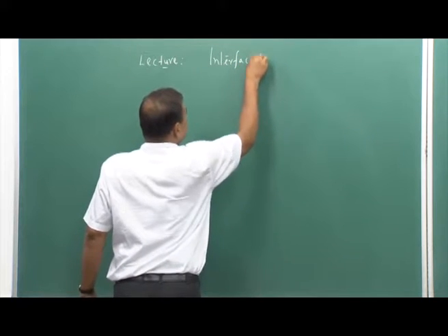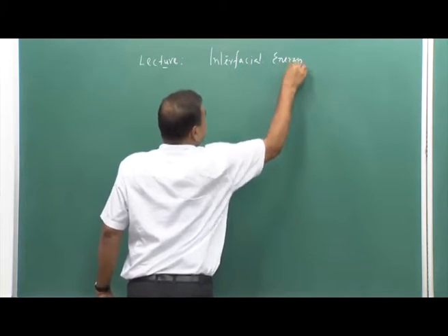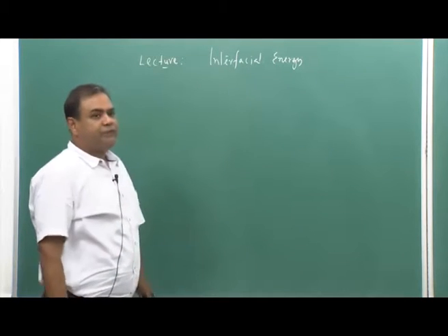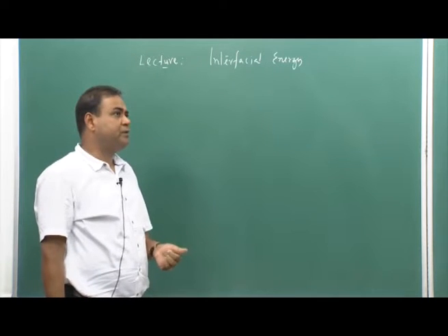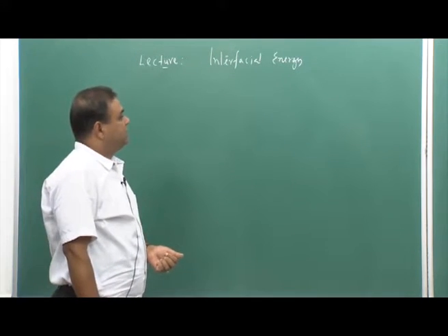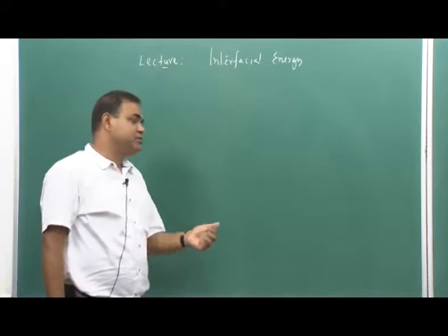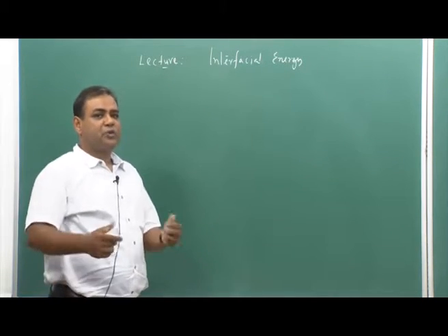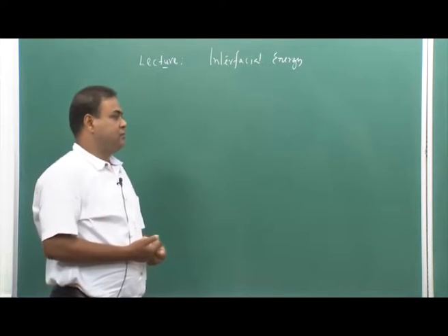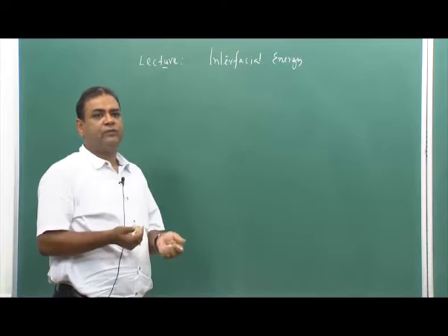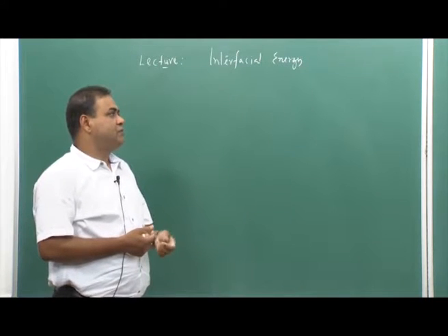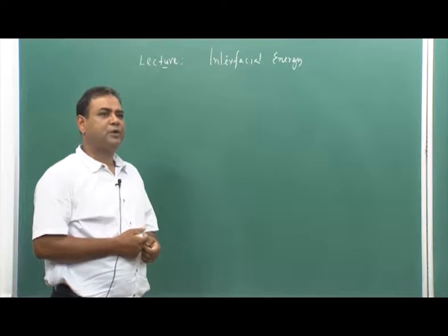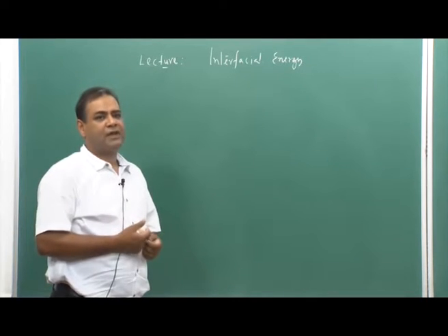So, in case of solid vapor, we have calculated how to calculate interfacial energy or surface energy from the bond concept. And then in case of solid liquid, we have seen that we can use some empirical formula, assuming that the bonds are not completely broken, it is half broken. And we have used one formula which is 0.45 delta H m, the melting enthalpy, divided by the Avogadro number. And then going through the same route, the number of atoms per plane, and getting the value of